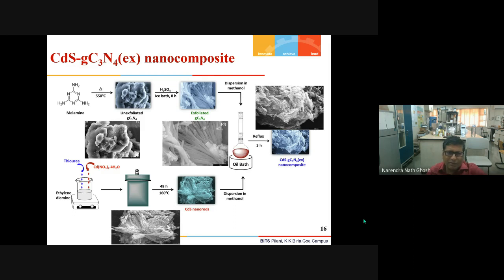And its SEM picture I have given. Now, you can see that it is a layered structure. But then we tried to exfoliate these layers by treating it with sulfuric acid in an ice bath. Surprisingly, after treating it with sulfuric acid for 8 hours in an ice bath, we could exfoliate these sheets, but due to the high surface tension, they become a tube-like structure. Okay. We got this exfoliated graphitic carbon nitride.